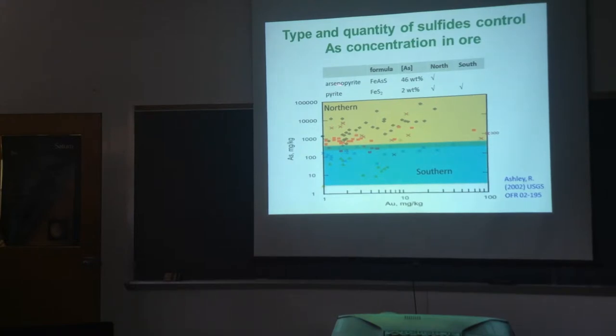You also have the occurrence of the mineral arsenopyrite only in the north, whereas in both north and south, you have pyrite that is arsenic bearing, and it can actually get up to 5 or 6 weight percent arsenic, and we call that arsenian pyrite. We distinguish that from arsenopyrite, which is a true arsenic-bearing mineral where arsenic is a stoichiometric part of the crystal structure. Whereas in the pyrite, as we'll see, the arsenic substitutes for sulfur, but it never gets up to more than a few mole percent on that crystallographic site. So, pretty big difference regionally between the north and the south.